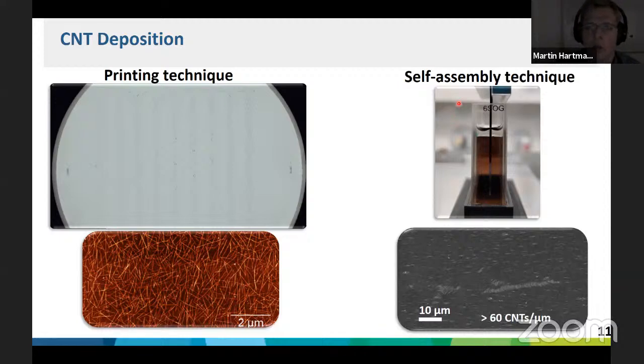But we also work on a self-assembly technique where we make use of the liquid-liquid interface between a liquid and a CNT dispersion. So here this color comes from the CNTs, which are swimming within the dispersion. And by such a self-assembly technique, we can achieve highly oriented CNT layers. So all the black part here are horizontally aligned CNTs with a density above 60 CNTs per micrometer. And here you see some defect lines. So it's not fully ideal yet, but I think this is quite a good level right now. So future high frequency CNT FETs will be built using this technique.